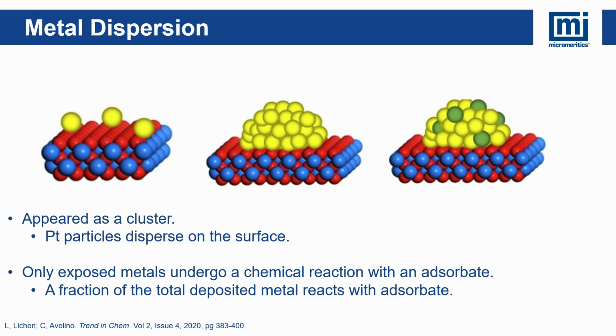Consider platinum, which is often deposited as a cluster on a support material. On the left figure, the yellow circles represent platinum atoms dispersed on an alumina support. However, the right figure depicts a more realistic scenario. Only the platinum particles on the surface, shown as green circles, are actively involved in the chemical reaction. Any platinum particles buried inside the clusters, which are not exposed to the surface, do not contribute to the reaction. Therefore, only a fraction of the total deposited metal is involved in the reaction with adsorptive molecules.